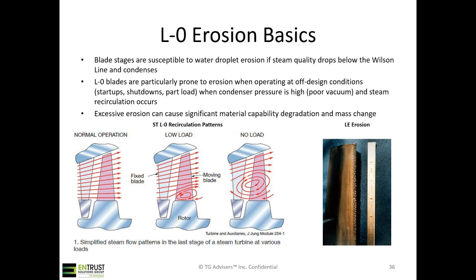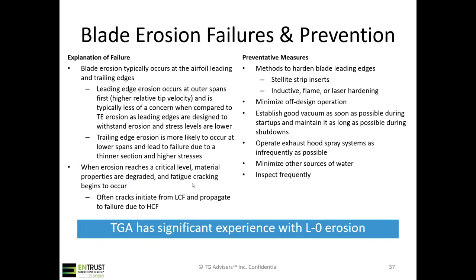There's a number of ways to try and mitigate this. Usually it involves hardening the leading edges with something like stellite shields or inductive flame or laser hardening. But overall, minimizing off-design operation, if you've got significant erosion, is always a good idea. Establish good vacuum as soon as possible during startup, and maintain it as long as possible during shutdown. Hood sprays can also drive erosion, so operate any exhaust hood spray systems, if they're present, as infrequently as possible, and inspect frequently. Erosion is kind of a tough one.